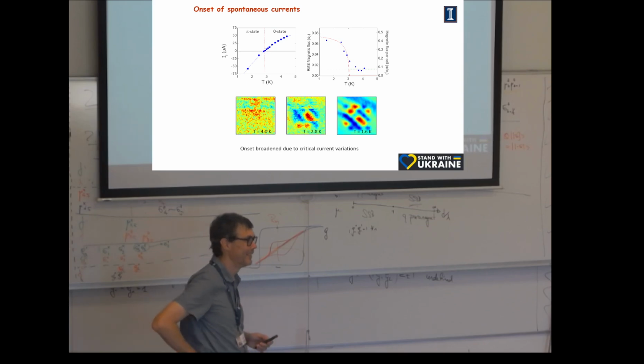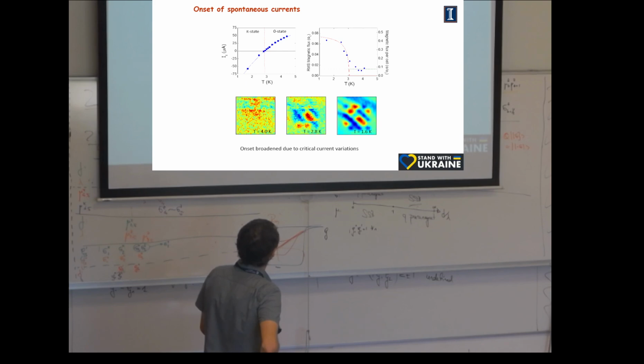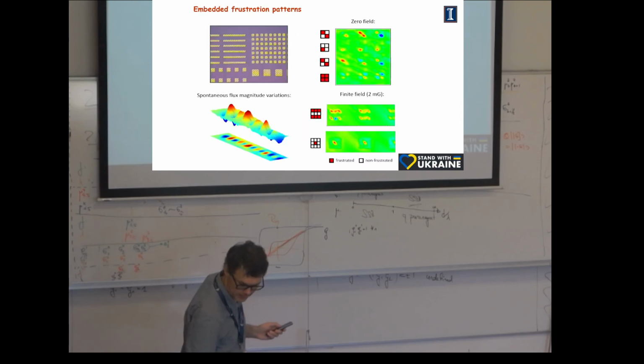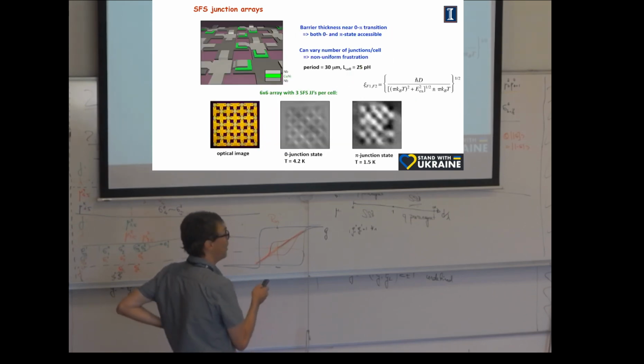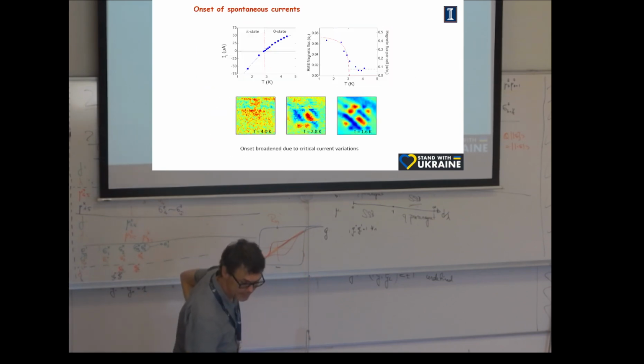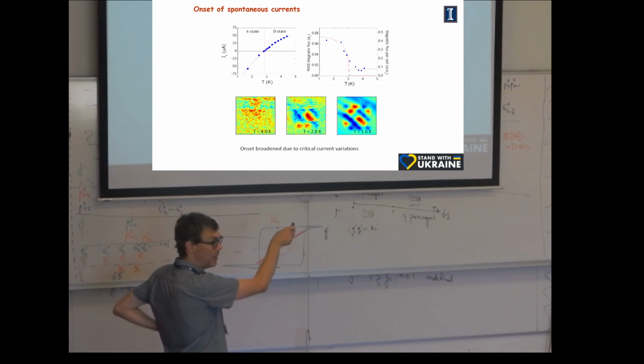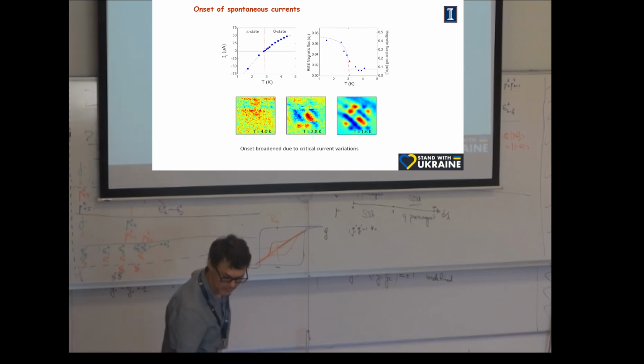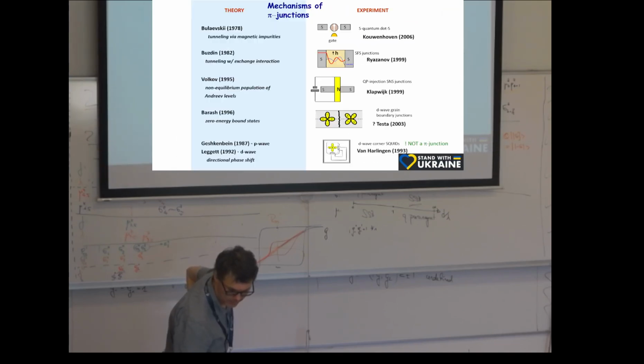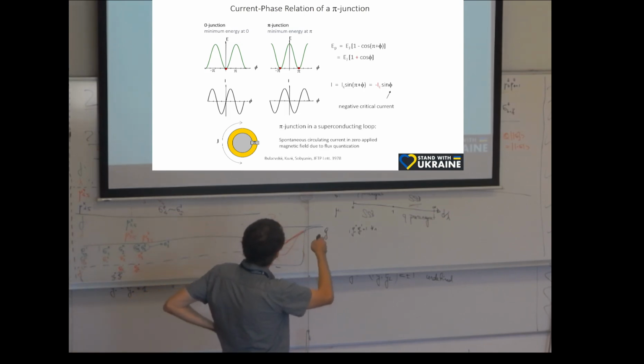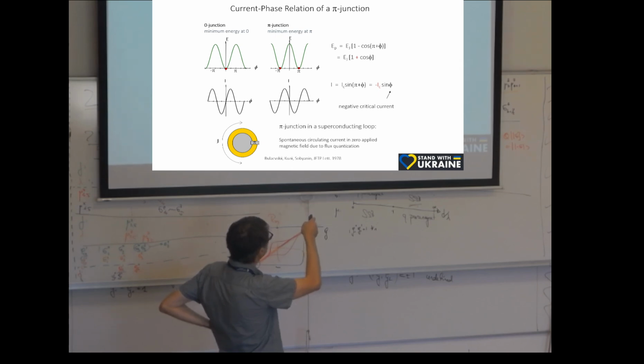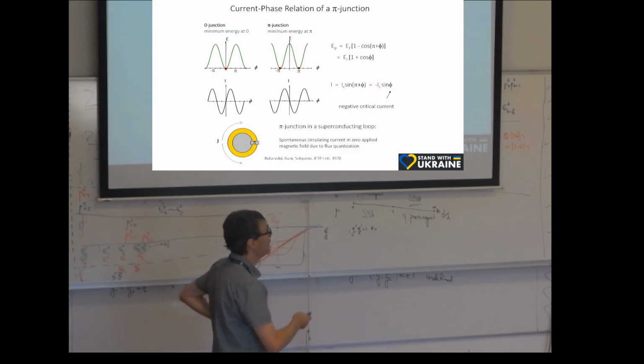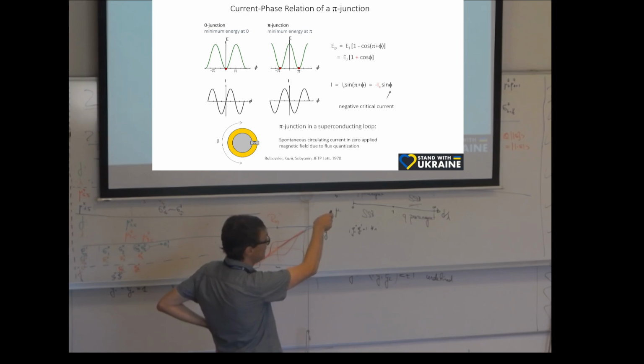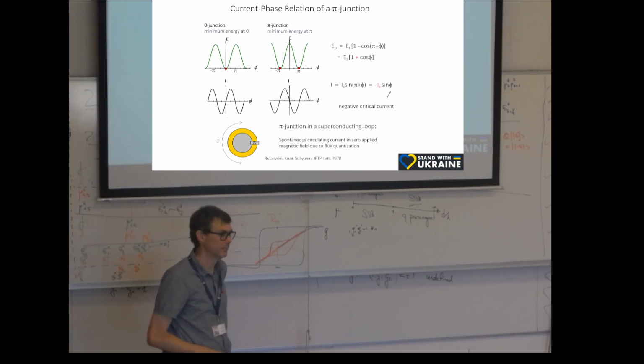What is this graph on the top left? IC versus temperature, right? This is the critical current? Yes. Why is it negative? Because it goes to pi. So now I can plot it as negative because I know in this phase there is a flux appearing, which means the Josephson current is actually negative. Right? So one way to say it is that the energy minimum is at pi, which is this expression. Another way to say it is that the critical current is negative. So you just take the pi out of sine of phi plus pi and put it in the amplitude of the critical current.